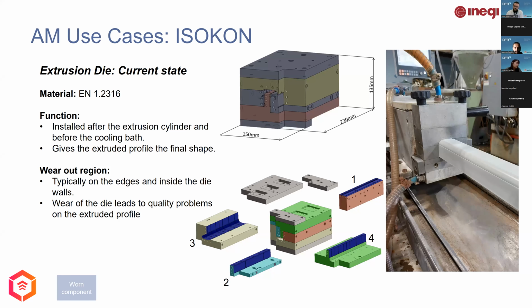The part chosen for this use case was the extrusion die used by Isokon. The die is installed on Isokon's extrusion line after the extrusion cylinder and before the cooling bath. It is responsible for giving the extruded profile its final shape. The die is an assembly of several parts, many of which show significant wear from its use. Typically, the edges and the inside of the die walls are the most affected areas. The wear on the die creates quality problems in the final extruded profile. As you can see in the figure on the lower left, highlighted in dark blue, the areas of intervention in this use case.